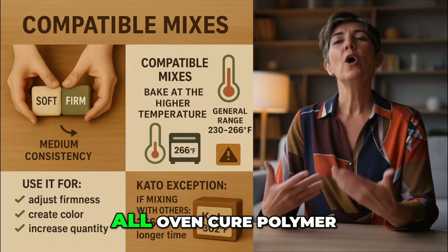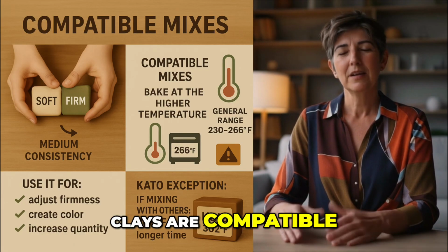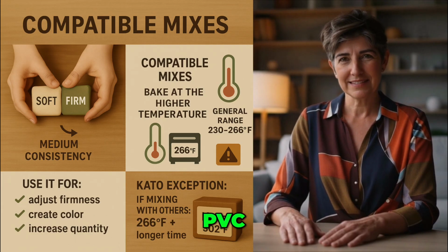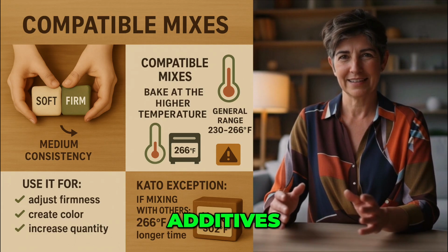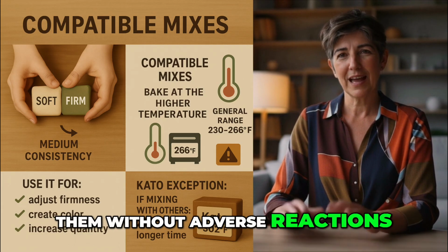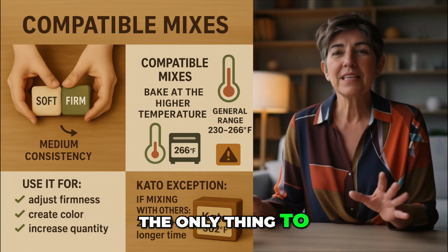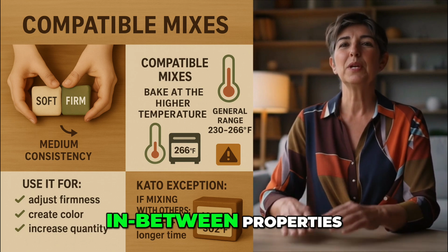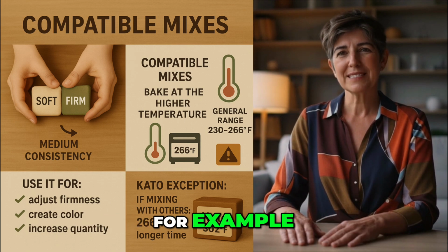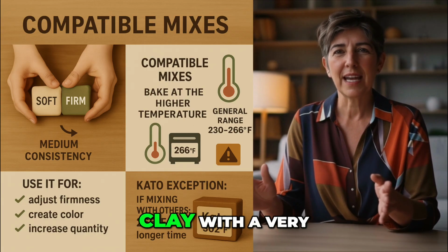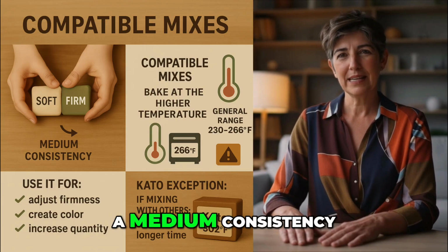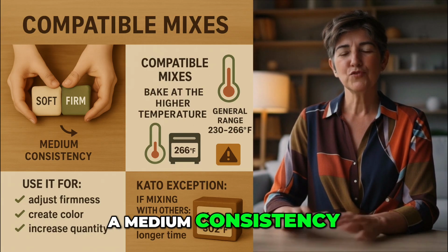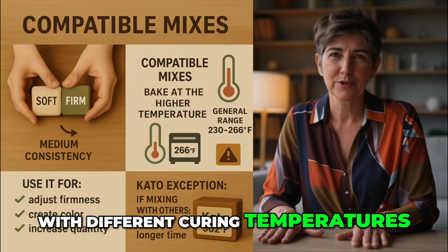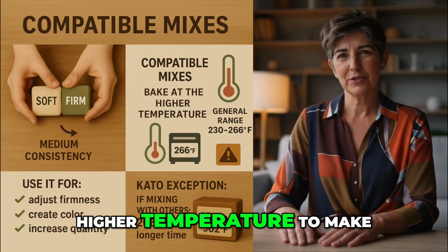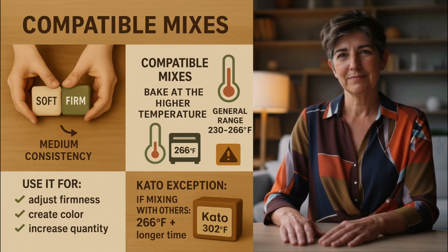In general, all oven cure polymer clays are compatible. They're based on the same resin, PVC, with different plasticizers and additives, and you can mix them without adverse reactions. The only thing to keep in mind is the blend will inherit in-between properties. For example, mixing a very soft clay with a very firm one gives you a medium consistency. If you combine clays with different curing temperatures, always bake at the higher temperature to make sure both cure.